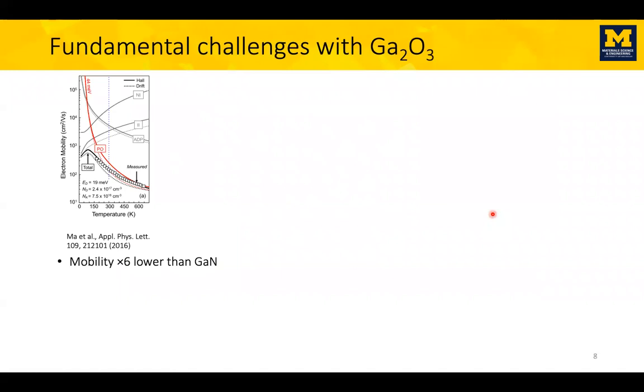However, there are many reasons why gallium oxide will not satisfy everything that we're looking for in the high power electronics field. For one thing, if we look at the mobility of electrons in this material, it is sizable. At room temperature, it has a value of around 100. Which is a good number, but it's still about 6 times lower than that of gallium nitride. In many semiconductors, we see mobility is more than 1,000.